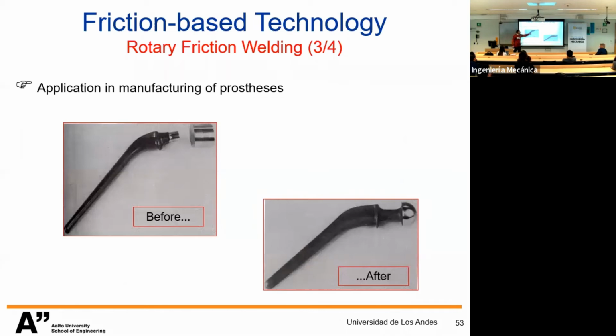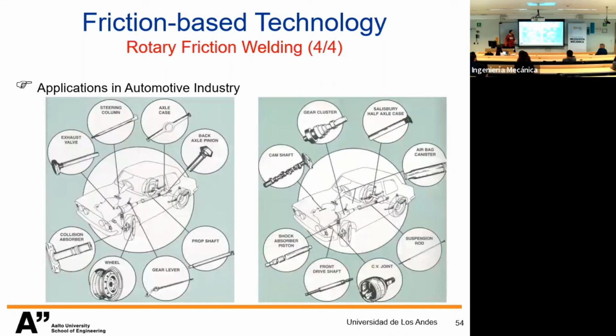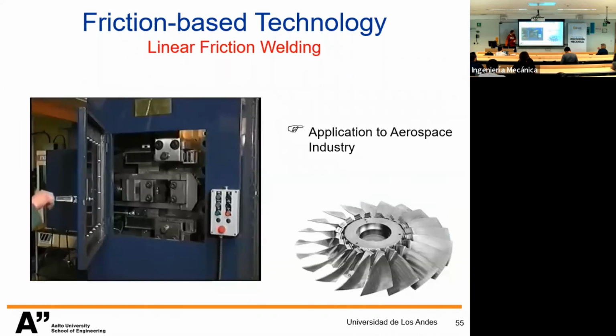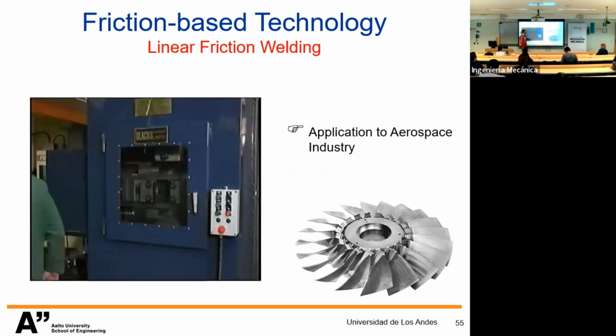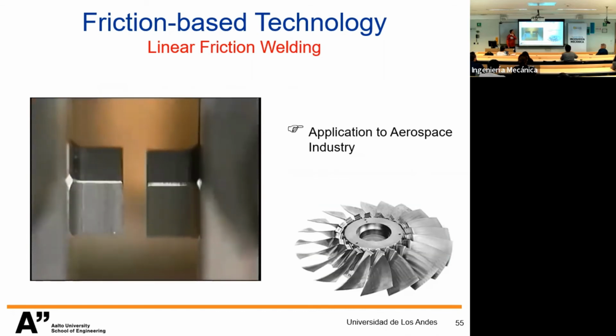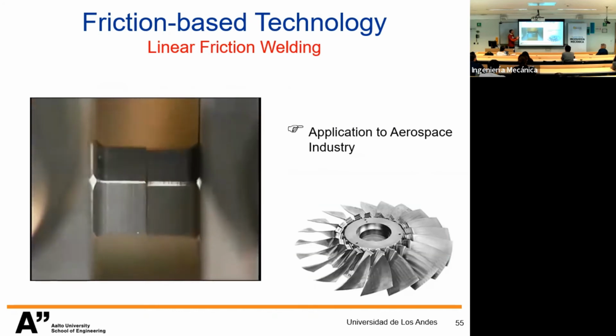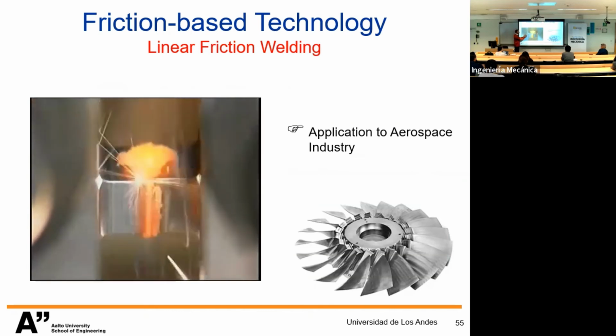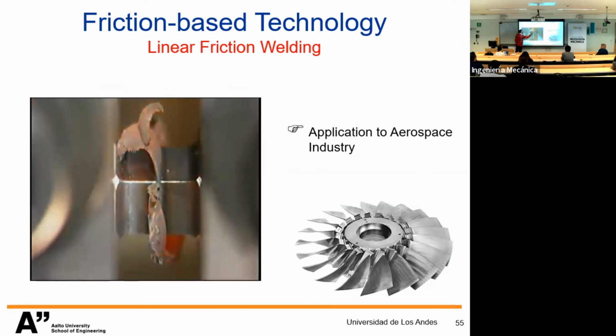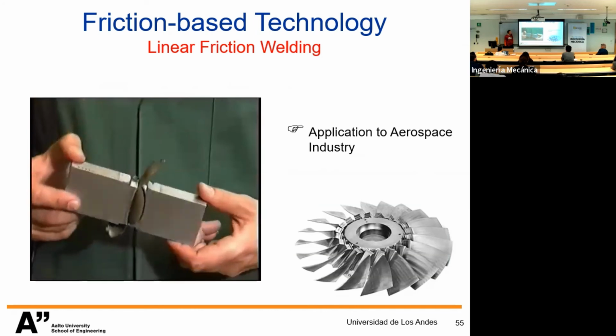There are applications to different materials, stainless steel, titanium components. A significant amount of applications, for example, nowadays airbags are welded in solid state because you have polymers inside the bag, so you cannot close the metal system with high temperature elements. Although the localized temperature is high, the amount of heat is low, so it does not affect the internal part. You also have possible applications for titanium-based alloys in linear friction welding. The disadvantage is that you momentarily expose the plastically deformed part to the air, until the flash forms and protects it, and it's possible to have a sound joint.